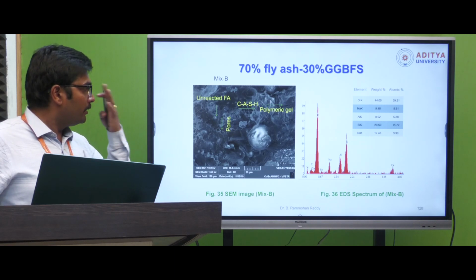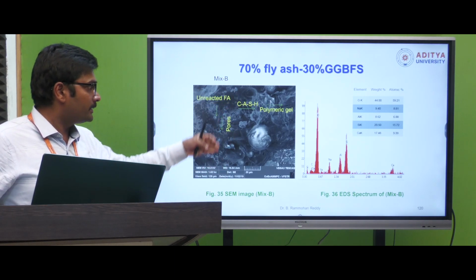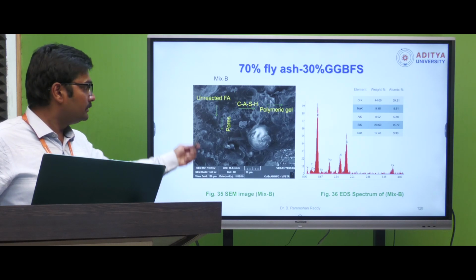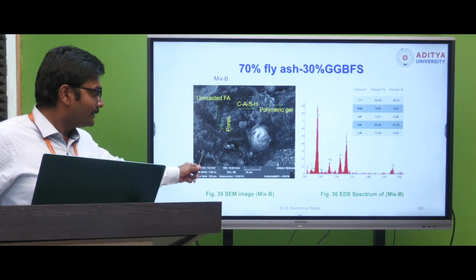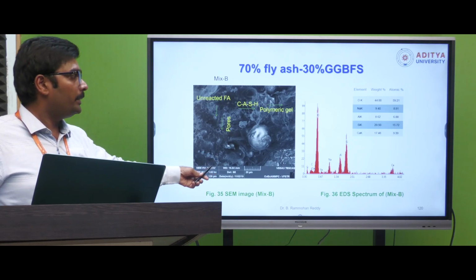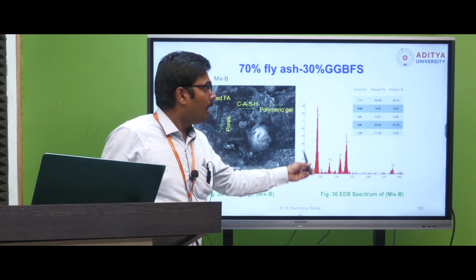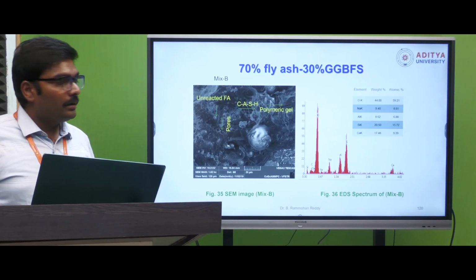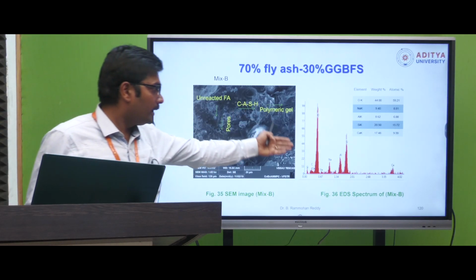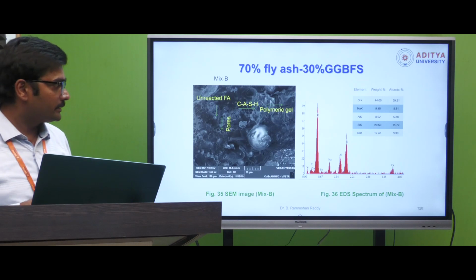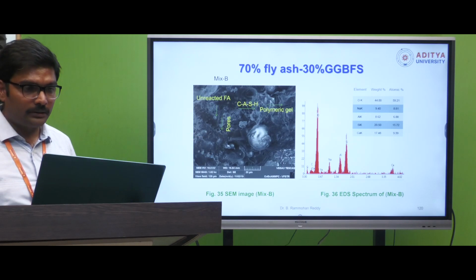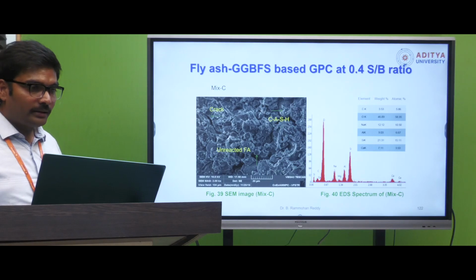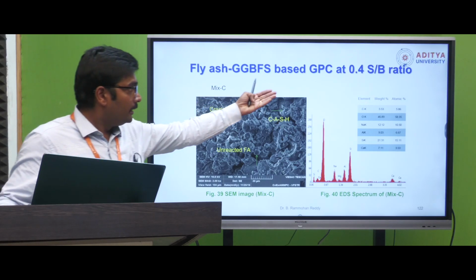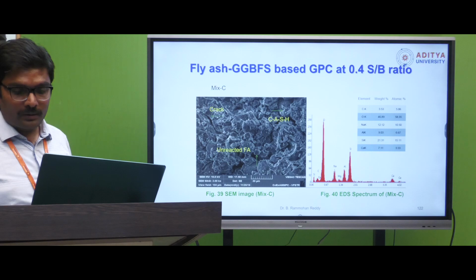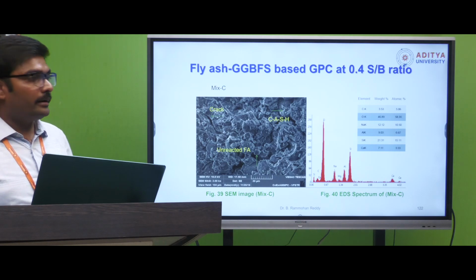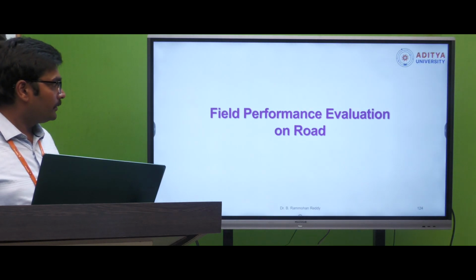So similarly at different proportions, 70% fly ash and 30% GGBS, how the microstructural studies are looking like. This is a SEM image, scanning electron microscope image, and this is the EDAX image, showing how the elemental percentage is identified here: silica percentage, alumina percentage, sodium percentage. This is after geopolymerization. Similarly, other studies were also highlighted at different sodium silicate solution to binder ratios, and how these gels will form.